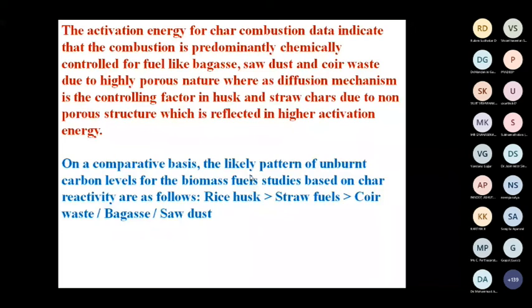The activation energy for the char combustion data indicates the combustion is predominantly chemically controlled for fuels like bagasse, sawdust, and coir waste due to their highly porous structure, whereas the diffusion mechanism is the controlling factor for husk and straw fuels due to their non-porous structure, which is reflected in the higher activation energy.